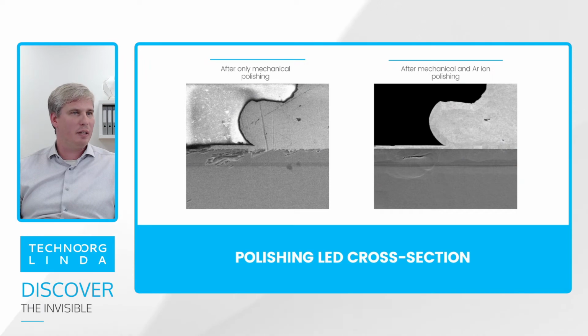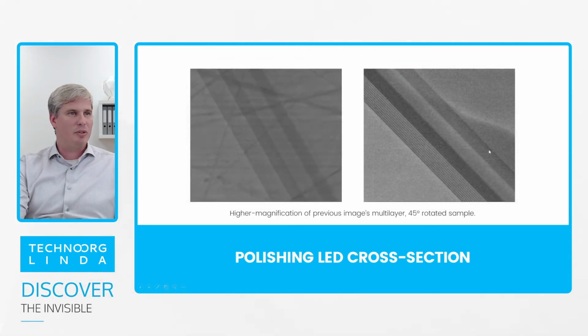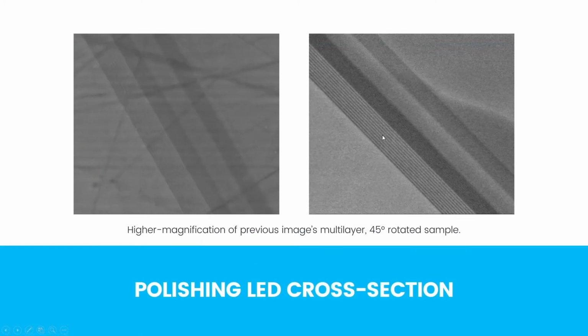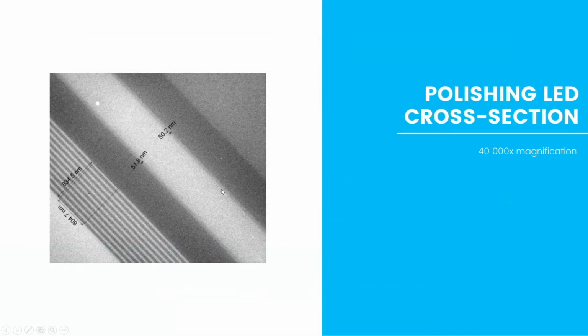Some other samples from the electronics. This is an LED cross-section. Here you can see a multi-layer part, probably it's a mirror. This was the area of interest, but after mechanical polishing, that was the finest result they could achieve. So they tried some minutes, it was 10 or 12 minutes of preparation by the ion beam, and that was the result. That was the difference between the two results. It's quite obvious. Even the smallest details can be measured.